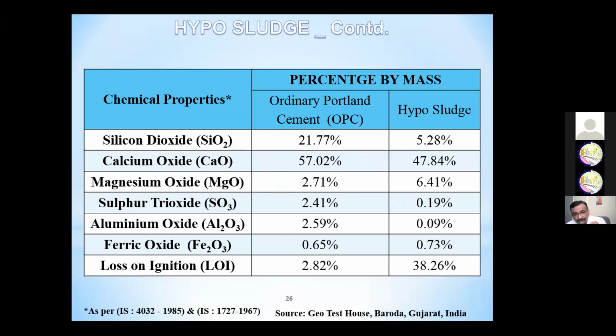Now, the hypo sludge properties compared with the cement properties. Here you can see the silicon dioxide (SiO2) is very low, 5.28%, but the calcium oxide (CaO) is 47.84%, so the binding property is largely available. This is the turning point of this particular work. If you go with the hypo sludge and the fly ash class F hybrid mix, they cover the cement properties. It is good.